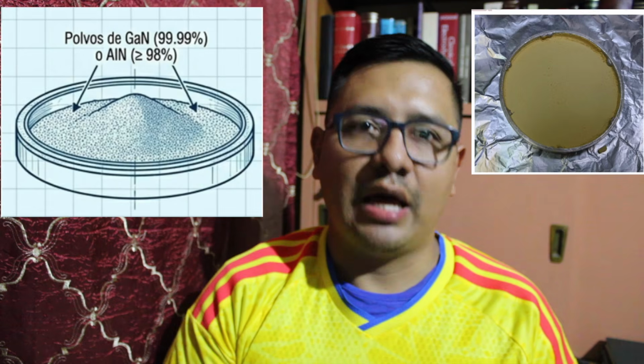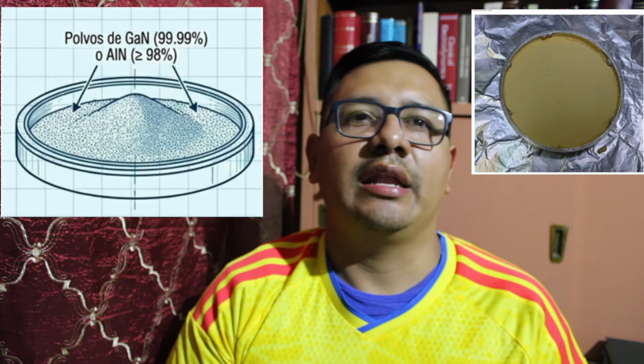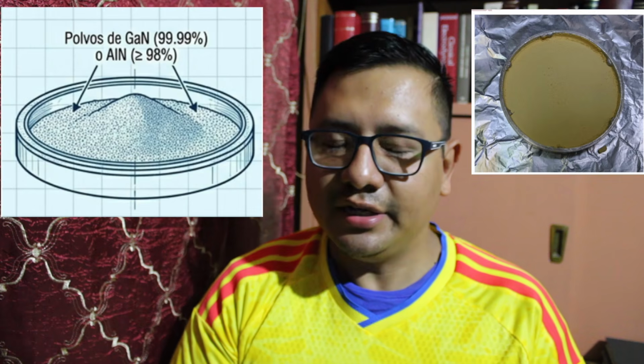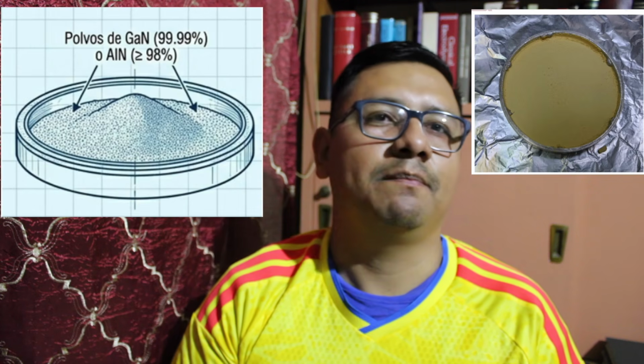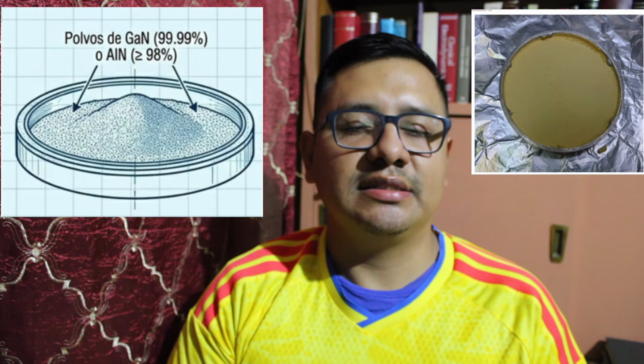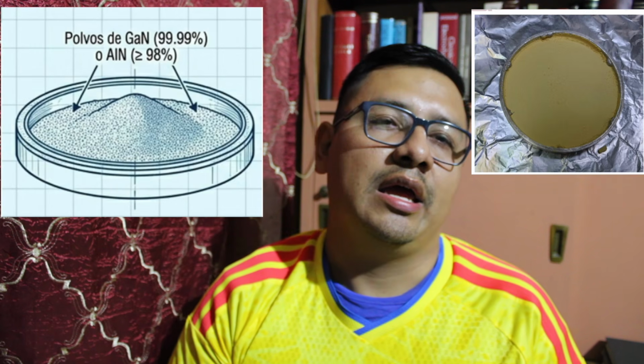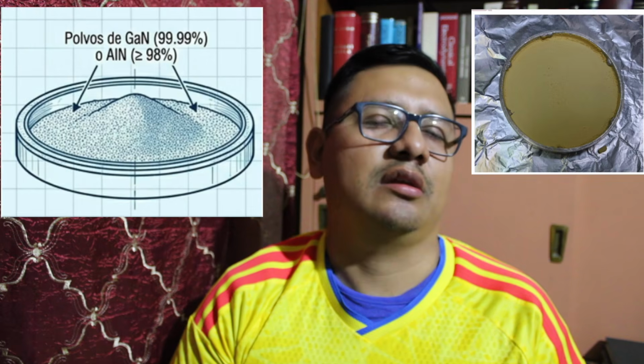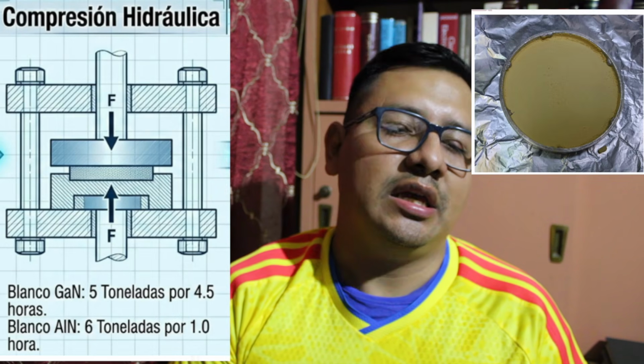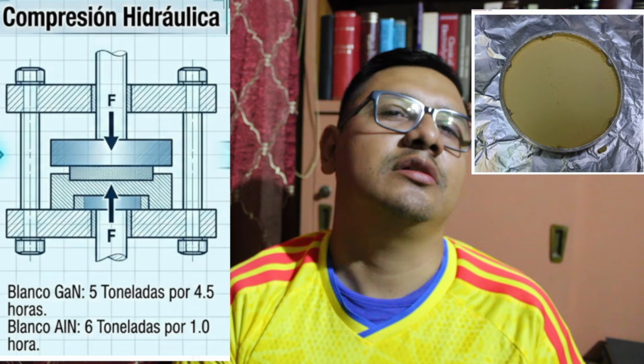In these conditions, we have been growing thin films, modifying the target composition. First, we did it with gallium nitride powders and aluminum nitride powders from Sigma Aldrich of high quality. We deposited these powders on a target holder, and we compress them until we create this solid target.